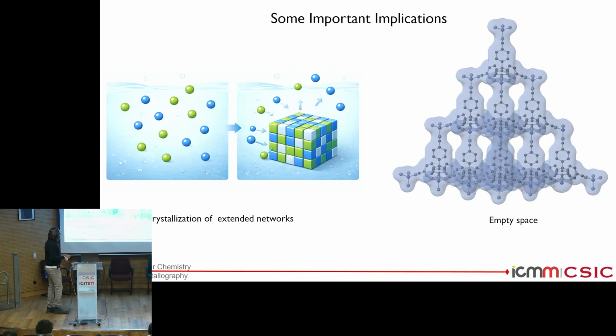And there are also a couple of important implications in Robson's work. First of all, he demonstrated that it is possible to crystallize coordination compounds with an extended network. And why is this important? Because when you are crystallizing something, typically you need some degree of reversibility. The stronger the bond between the components that make up your crystal, the more difficult it becomes to get something crystallized, because you need some reversibility to correct the defects that happen during crystallization. All right, so in coordination chemistry, it was typically accepted that if you have multiple bonds at the same time, you will have just some amorphous junk rather than some crystalline material coming out of your reaction.